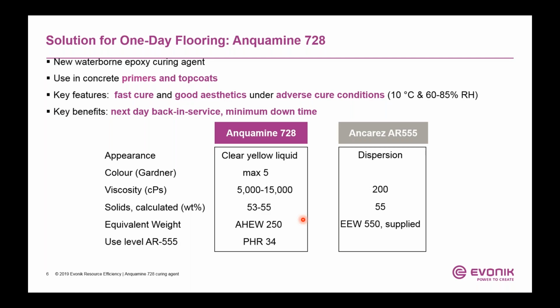A little bit more detail about Anquamine 728. It's a very low color aqueous solution in water, about 55% solid, has a medium viscosity, and the use level with the solid resin dispersion AR555 is about 34. Anquamine 728 is based on a proprietary neoamine technology that gives the very fast cure speed.